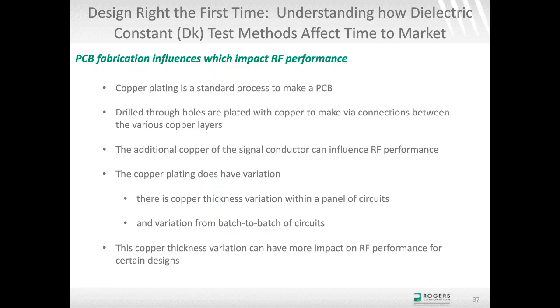Another experiment I did was copper plating, and copper plating thickness will vary from circuit to circuit. That's pretty normal. So a lot of circuits that are plated through hole, you drill the hole through, you plate copper through. That's how you make connections through the thickness axis of the circuit. And this copper plating thickness will vary, and on circuits on one panel, there's going to be copper thickness variation, and then panel to panel, there'll be copper plated thickness variation as well.